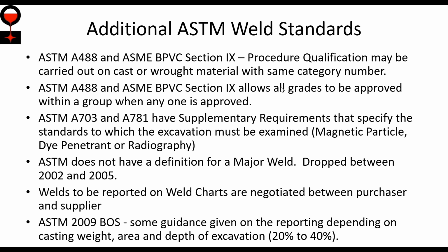In ASTM and ASME, I can approve all the grades in a group when any one in the group is approved. Now in ISO, they require that I have the most highly alloyed, the most difficult to be welded to qualify all of the members of a group, whereas ASME and ASTM allow me to use any grade in that group to qualify. ASTM 703 and 781 have supplementary requirements for examination.